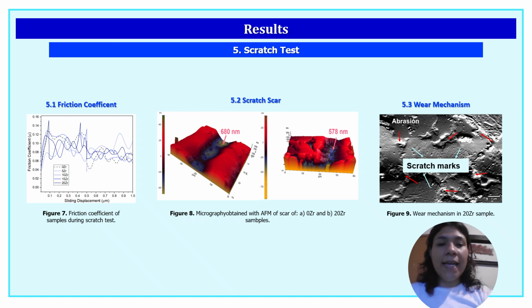In figure 8, a comparison of the scratch depth between the 0 zirconium and 20 zirconium samples is shown, revealing a reduction of up to 102 nanometers in depth for the 20 zirconium sample. This was attributed to the addition of zirconium increasing the surface hardness of the samples and the formation of the zirconium-2 nickel intermetallic. Additionally, figure 9 shows the wear mechanisms.